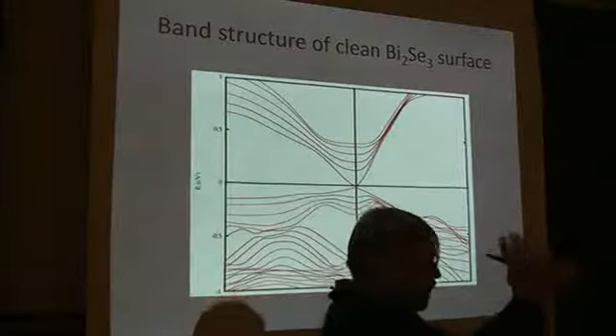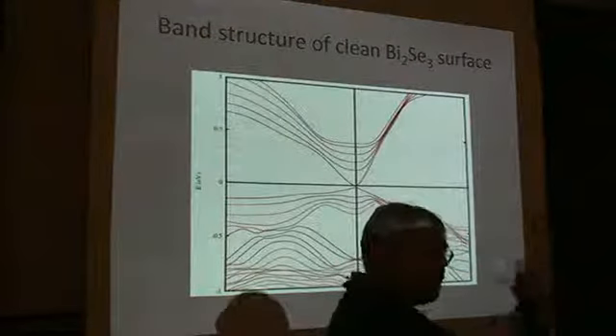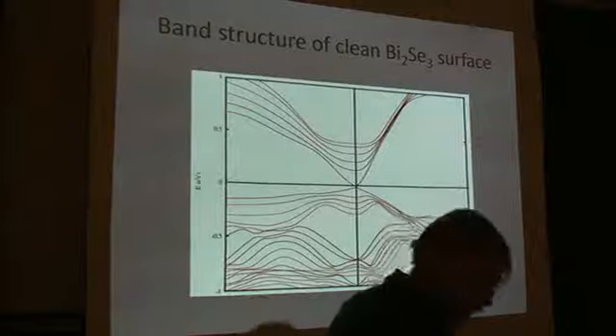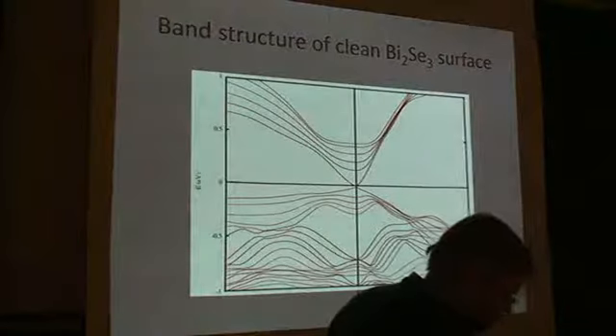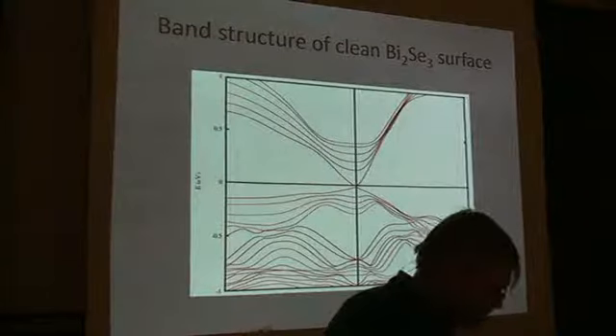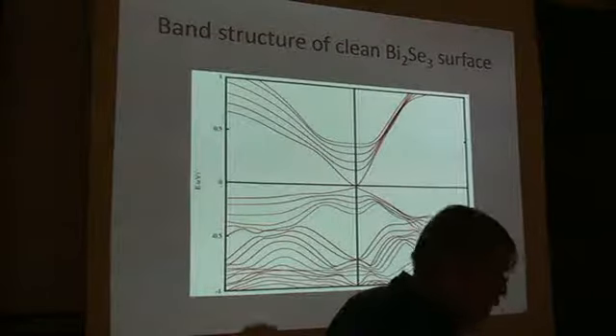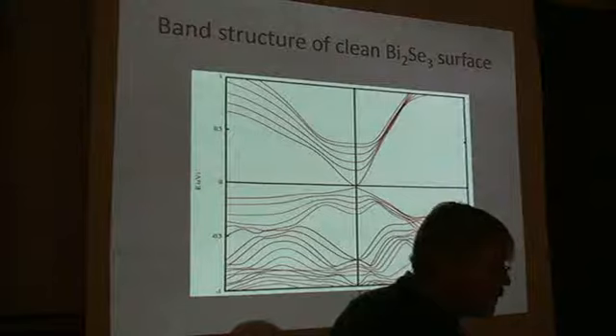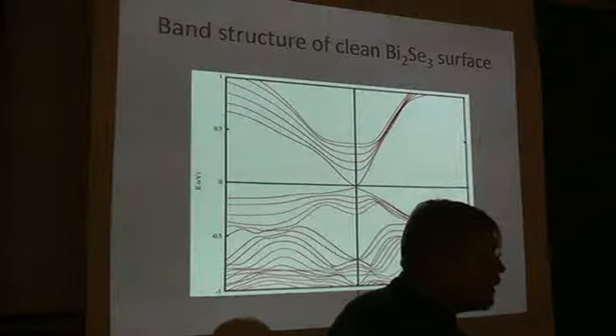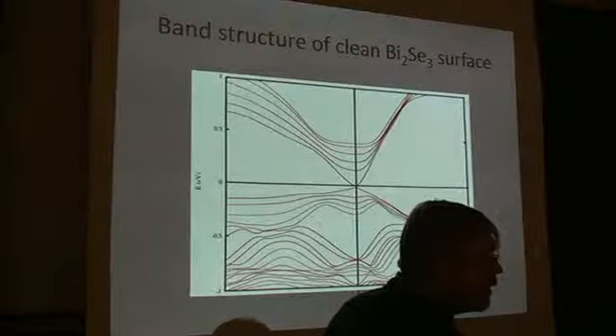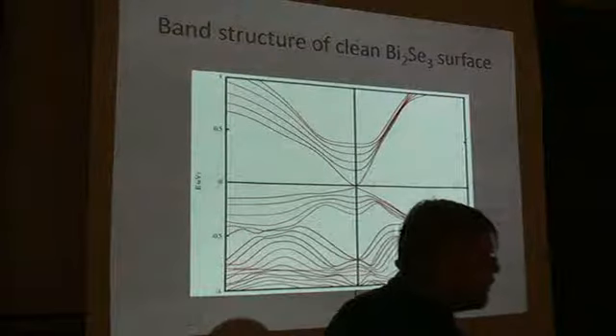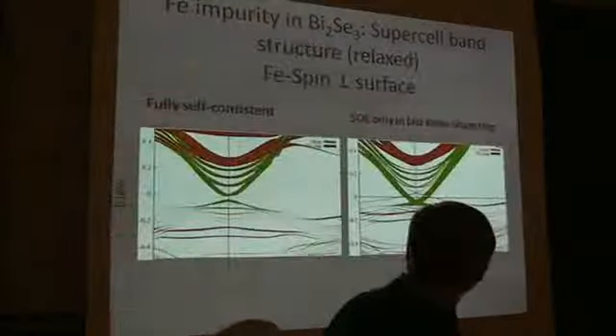Even for the band structure, it doesn't have to come out as exactly a graphene case. So is that because of the presence of a quadratic term in k dot p perturbation theory, or because of the band structure? There must be a k dot p explanation for this. I'm sure there is. Well, if this is literally two crossing lines close to the point, and they have the same slope, they don't have the same angle. But then there's a cusp in this line. Yeah, exactly. No, but the cusp of the line is exactly what's left over of the Dirac point.